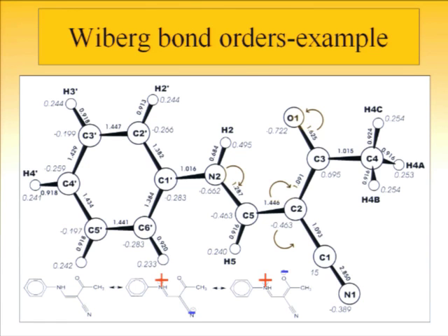Those numbers here are so-called bond orders. So you would expect chemically here a single bond, and actually the bond order is quite close to 1. You would expect a triple bond here, 2.85 is quite a good estimate. Here the single bond. But if you look here, you would expect 3 single bonds. This one is quite single, 1.016. This one is definitely not double. This is 1.3 approximately, and this one is only 0.7.